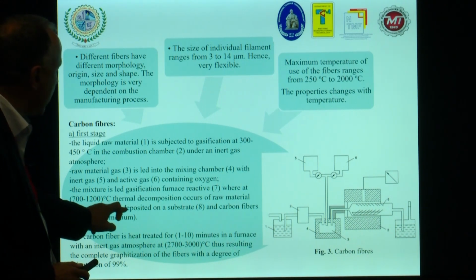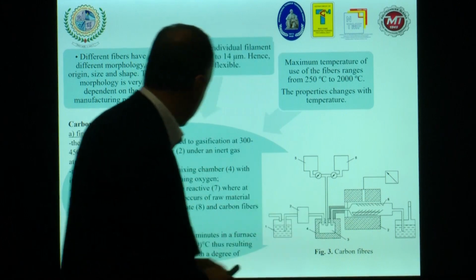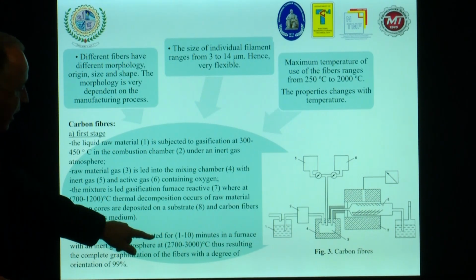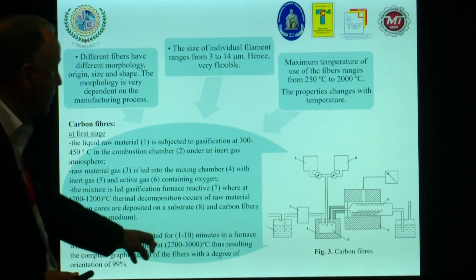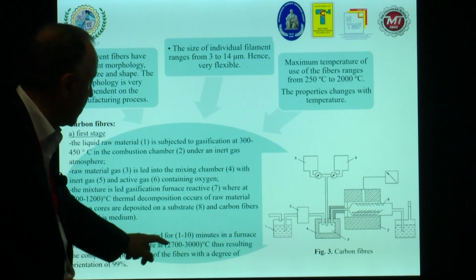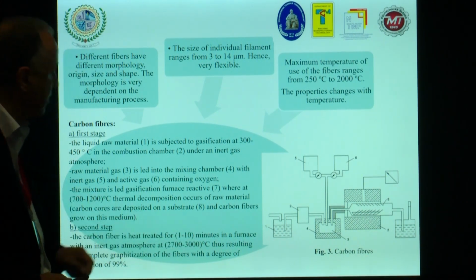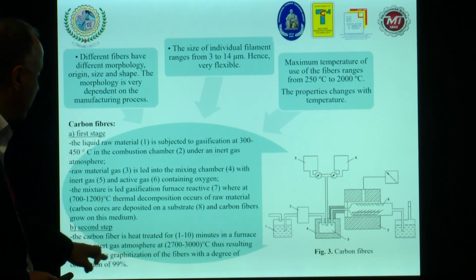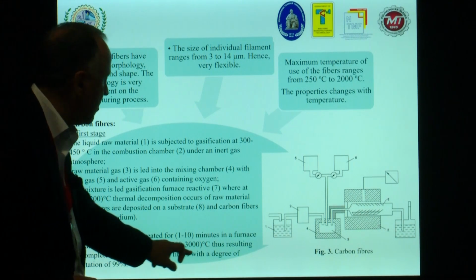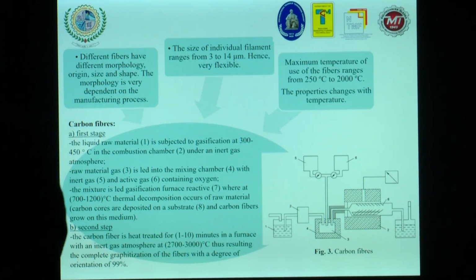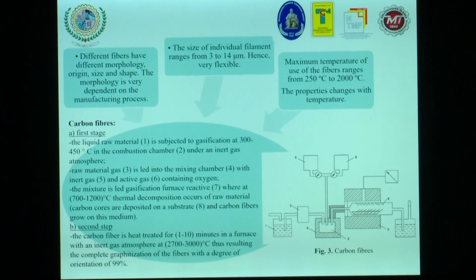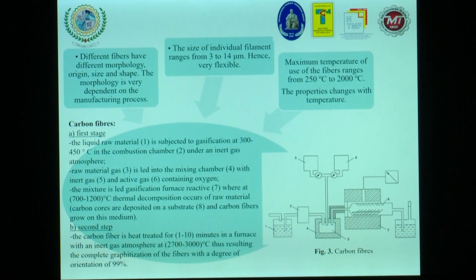The carbon cores are deposited on the substrate number 8. And in the second step, the carbon fiber is heated for between 1 and 10 minutes in a furnace with an inert gas atmosphere, and look at the temperature, 2700 to 3000, thus resulting in the complete graphitization of the fiber with a degree of orientation around 99%. So it's also a general sketch of how we can get the carbon fibers. Of course, if you try to find it on the internet, you can find the details of all the technology, including the technological parameters.